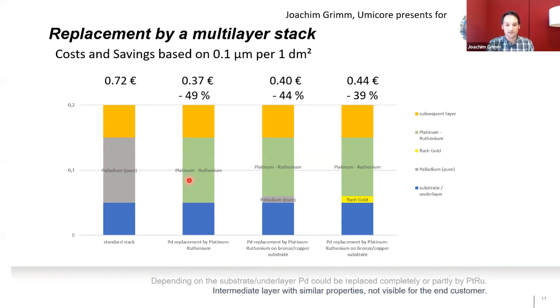So instead of palladium, you use the platinum as an intermediate layer, and your final layer on top gives you a saving just in the palladium layer of 49%, because the palladium price is that high at the moment. So I talked mainly now as a reference or as some example about sterling silver. So what if you don't have sterling silver as your base material?